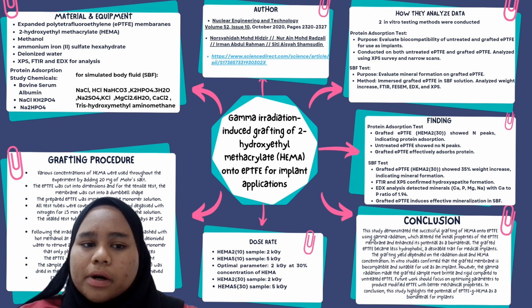However, the gamma radiation made the grafted samples more brittle and rigid compared to untreated ePTFE. So future work should focus on optimizing parameters to produce modified ePTFE with better mechanical properties. So the study highlights the potential of ePTFE-g-HEMA as a biomaterial for implants.